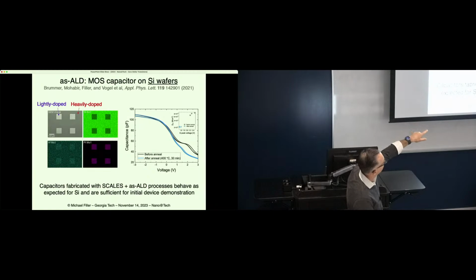Two, the interface state density starts, not great, but we can make it better with a forming gas anneal after the fact. Okay. So we're able to get interface state densities in the low 10 to the 11s, right? This is not breaking any records for sure. Right? But we can create these devices, and we can at least start to engineer their interface state density.